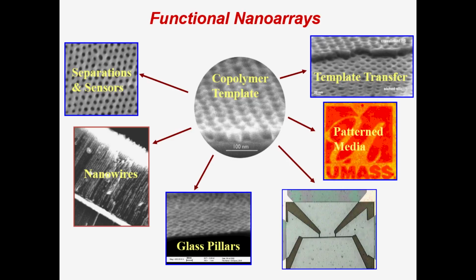Alternatively, I can take this, and the film happens to be on a silicon substrate, and I can use an ion beam to etch into the underlying substrate. The substrate is silicon. It's a semiconductor. I let an oxide grow back, and I can evaporate a metal on the surface of that, and I have a capacitor. It's very simple. No lateral order in this particular case whatsoever. I'm just using the copolymer as a template to transfer this pattern to the underlying substrate.